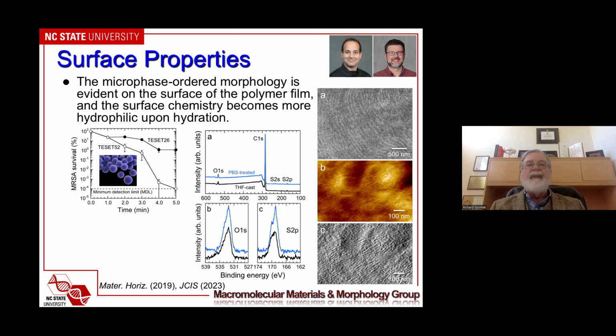And that's simply due to the fact that at the surface, we have these structural elements that provide pathways. Note that if you go to a typical disinfectant, it'll say about 2 minutes. So we are well within that, but the big difference is this is not a point-in-time solution. This is continuous. This is self-cleaning, and it does not add to solid waste.